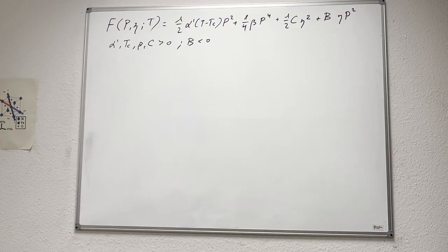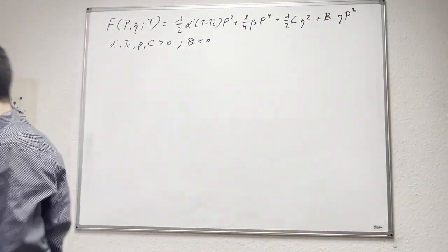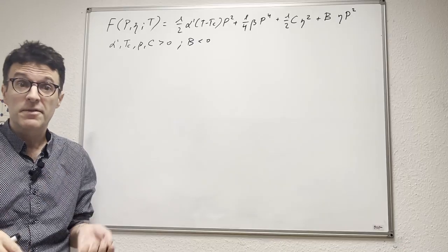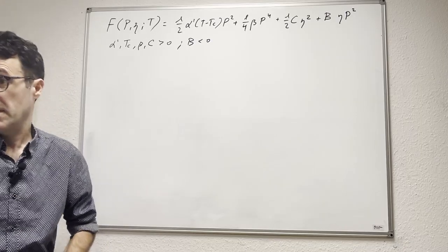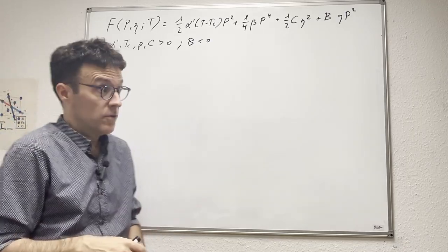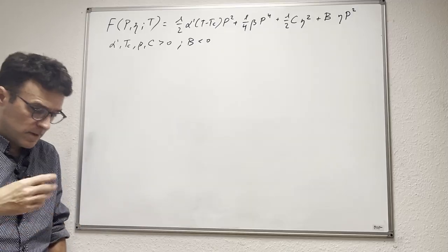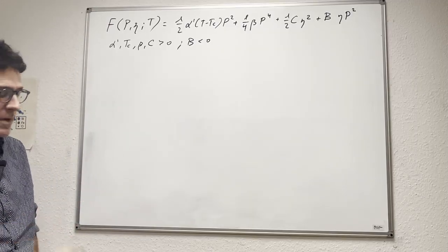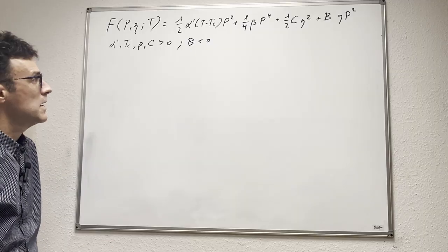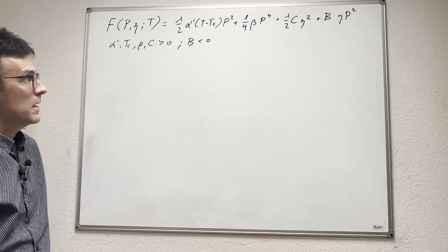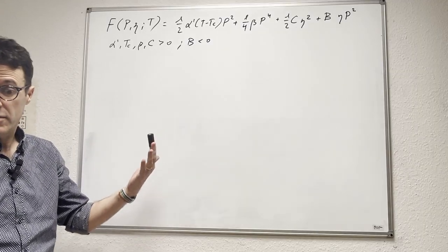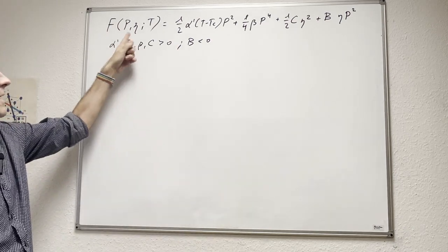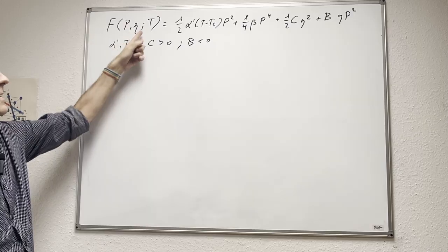All right. Now, the other day we ran an exercise in which we said, okay, let's imagine we can control the strain from the outside, and we use the strain as a parameter. That, of course, is fine, and it's very similar to what you need to do when you grow a thin film and you fix the epitaxial strain to that of the substrate. But now here we are going to use the strain not as a parameter, but as a variable. Okay, so it is on the left-hand side of this semicolon.